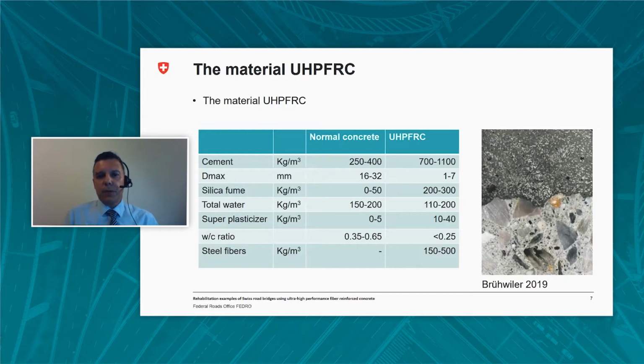The water-to-cement ratio in ultra-high performance fiber reinforced concrete is less than that of a normal concrete. In an ordinary concrete, the water-to-cement ratio is between 0.35 to 0.65, whereas in ultra-high performance fiber reinforced concrete, the water-to-cement ratio is less than 0.25. So, due to the low water content, superplasticizers are essential for the workability, and they are in much higher content than that for a normal concrete.